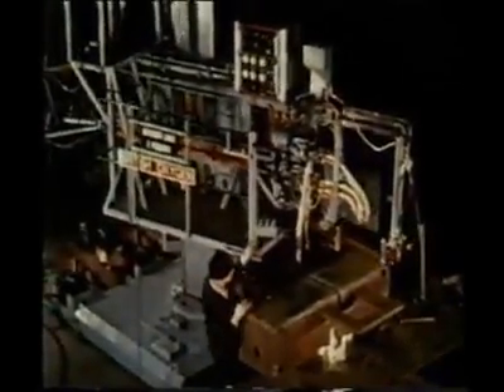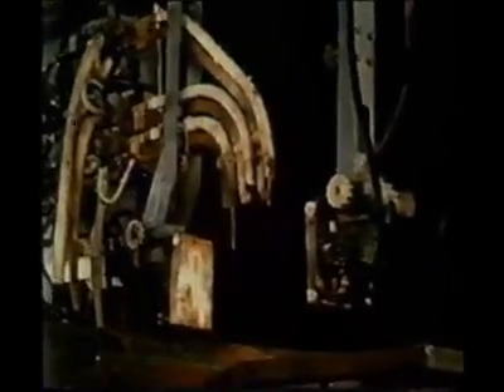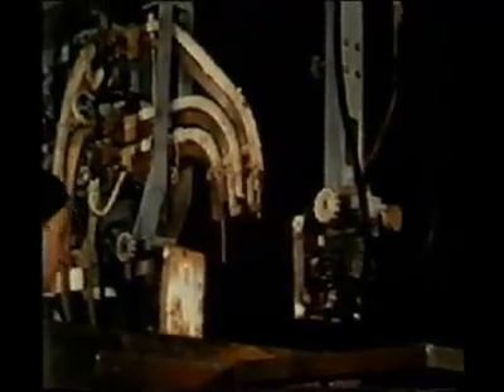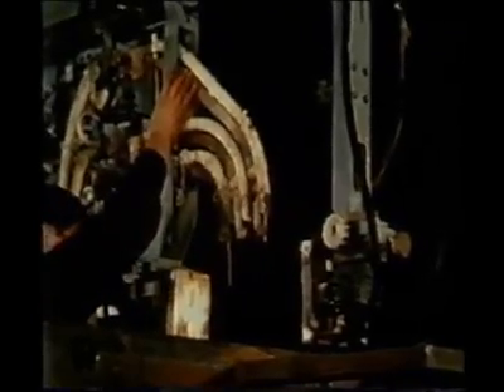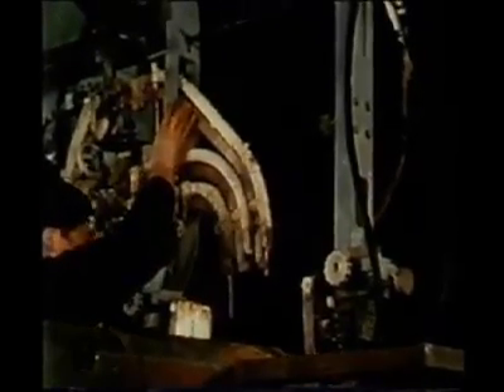The process can be applied to circumferential seams using a technique developed by British Oxygen, as in this example of a 5-foot diameter cylinder with a 2.5 inch wall thickness. Here, a machine was specially developed for the customer to use on a wide range of applications, including boiler drums, forgings, and ship's stern frames. By changing columns, the welding length can be increased. Additional shoe arrangements enable T-butt joints, corner joints, and circumferential seams to be welded.